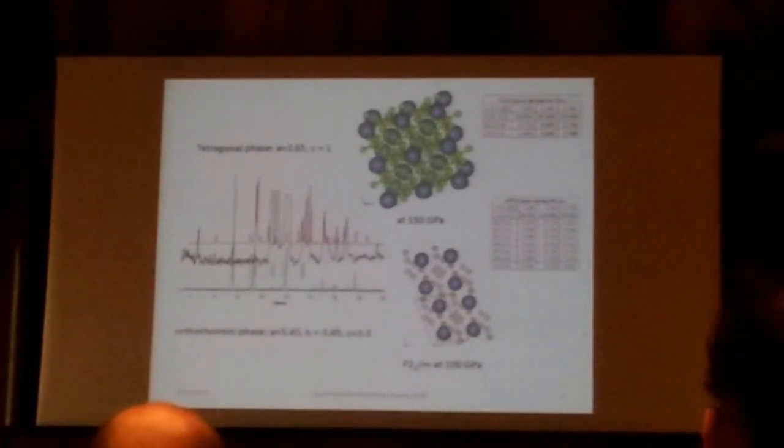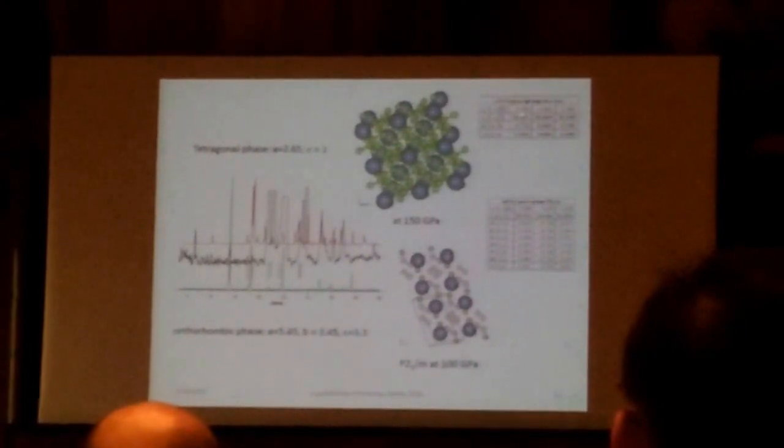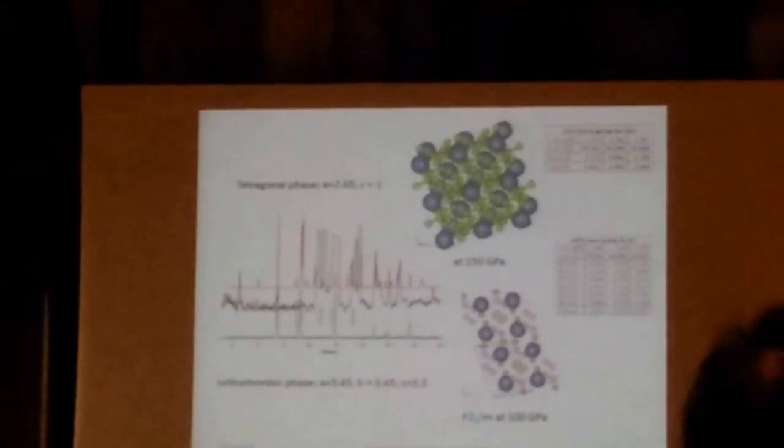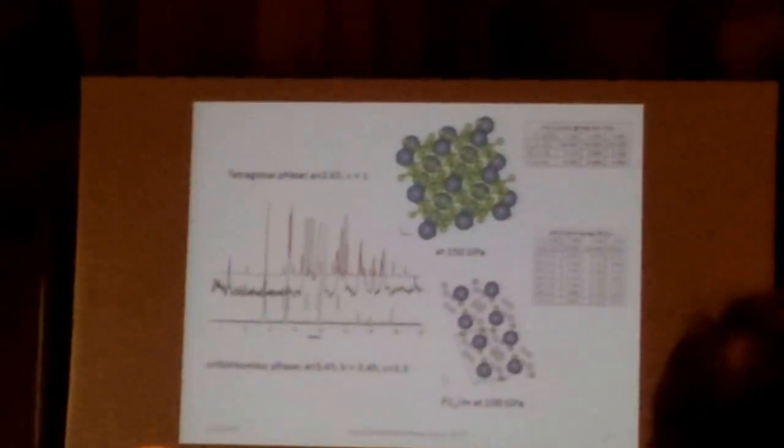A tetragonal phase with an a which is smaller than what is predicted in their cubic structure. But c, I'm sorry it got swallowed up by this figure here, but c is about 5 times what they predicted. Now, it doesn't mean there's anything wrong with the calculations. It could certainly imply that what we are synthesizing is a disordered solid or something where there is substitution disorder, and therefore we're not able to get to that phase yet, which may mean that we either have to have more hydrogen or a higher temperature of reaction to make this CaH6 phase, which has been predicted.